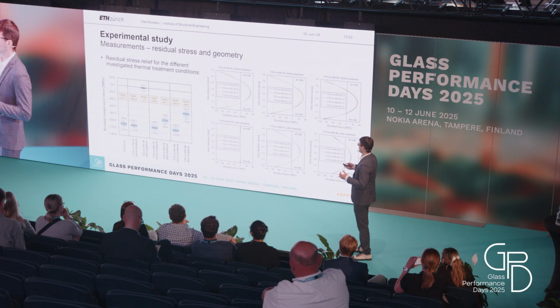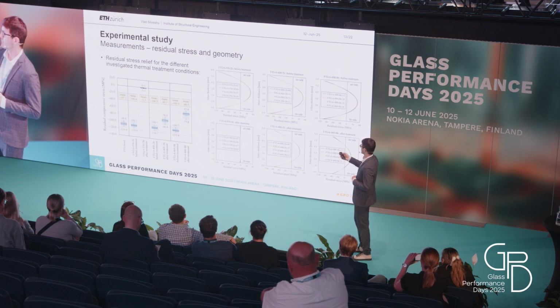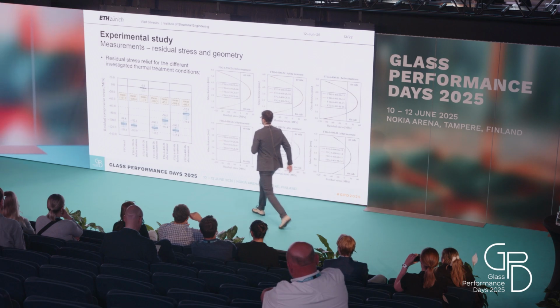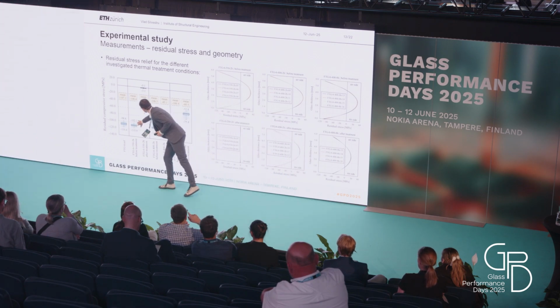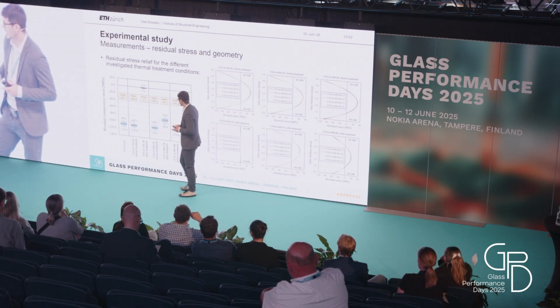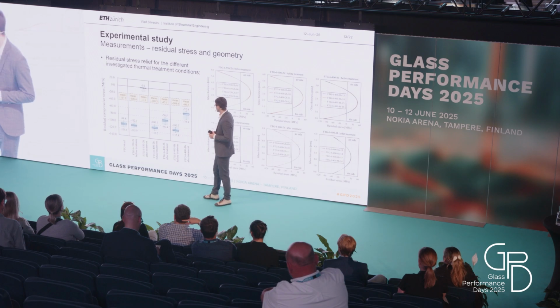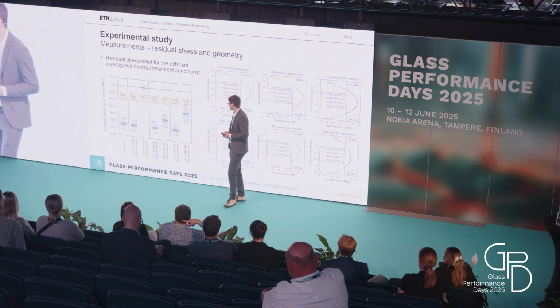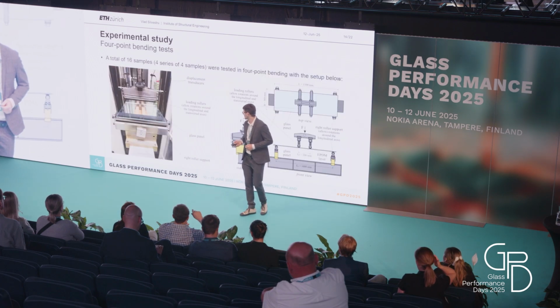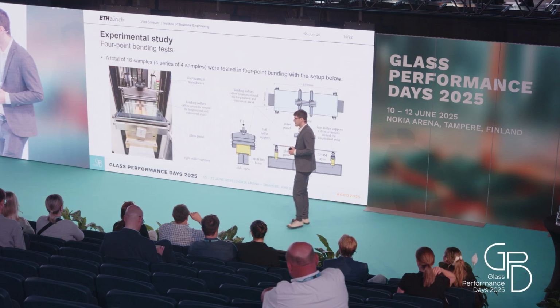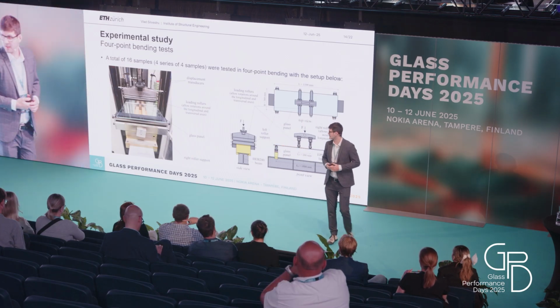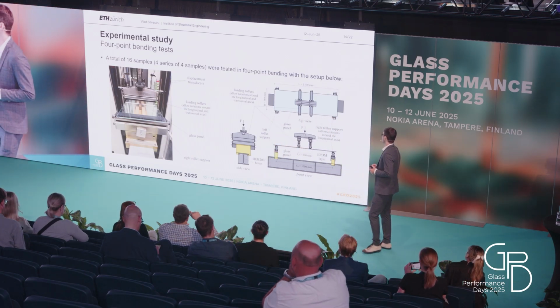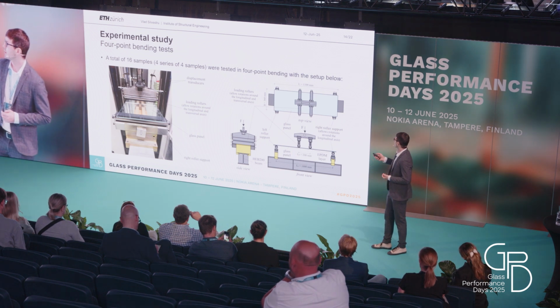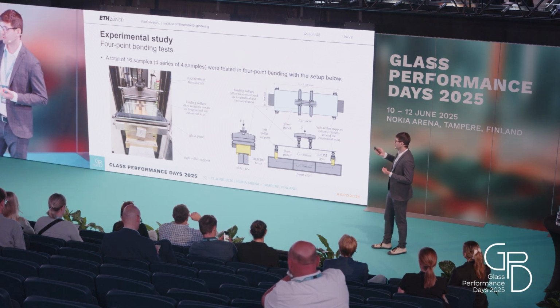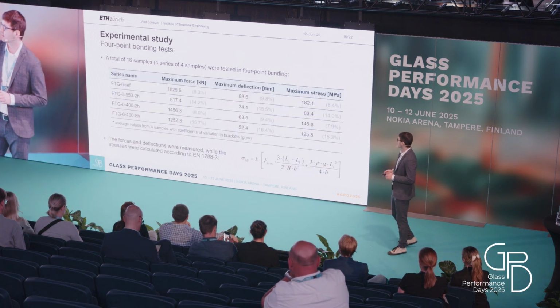If we look at the mean value, also here it can be seen that at 550 degrees, if we compare these with these, we got completely rid of the residual stresses. At 400 degrees, there was only this partial reduction. In the next step, I conducted a 4-point bending test. It's the test from the standard, nothing special. We measured the force and also the midspan deflection.